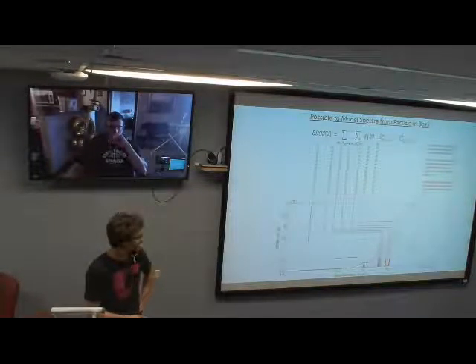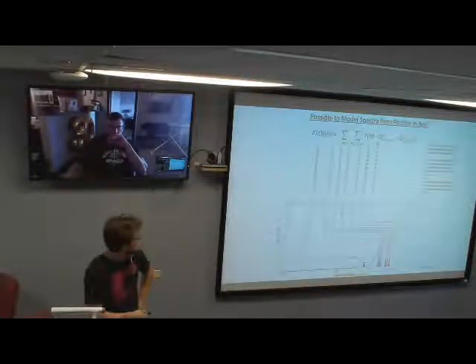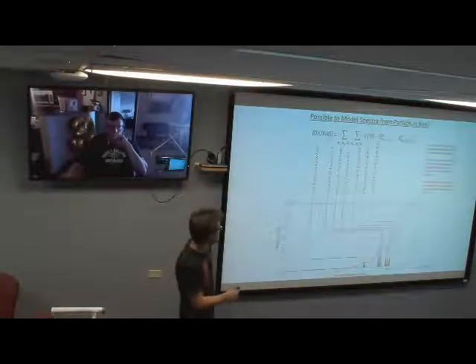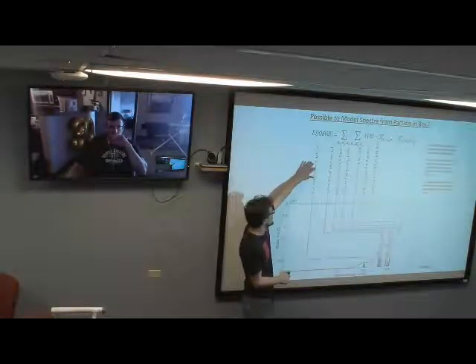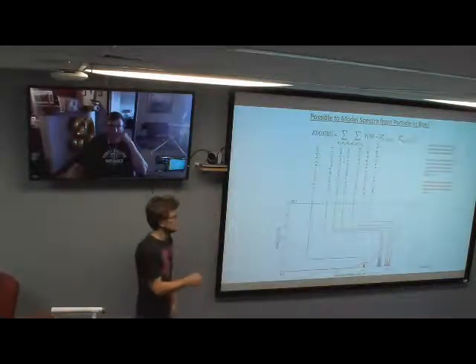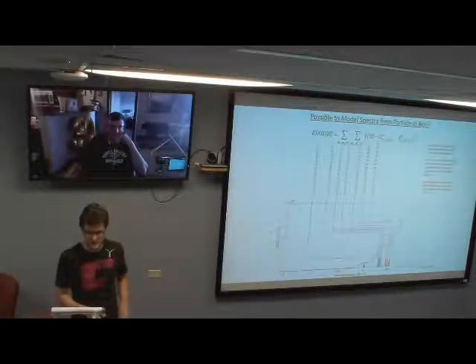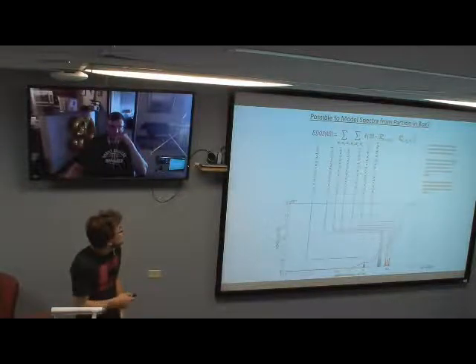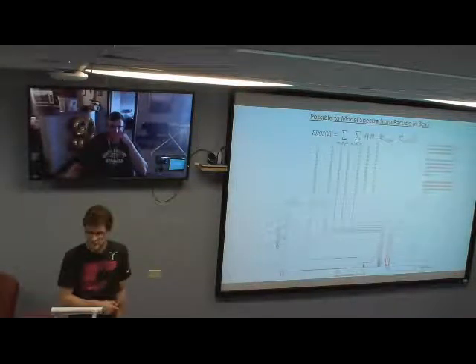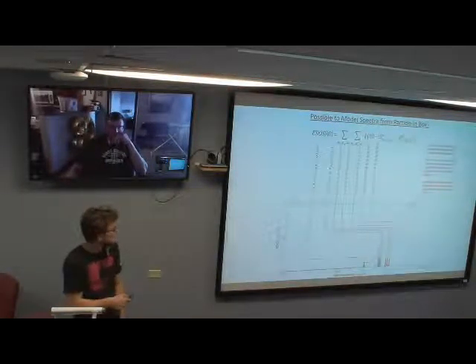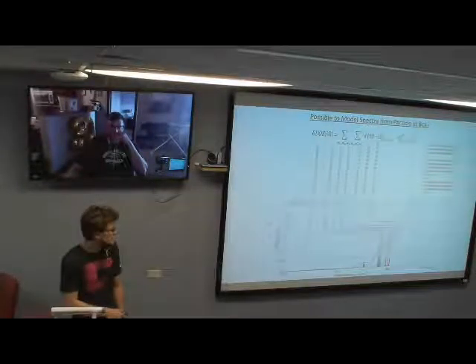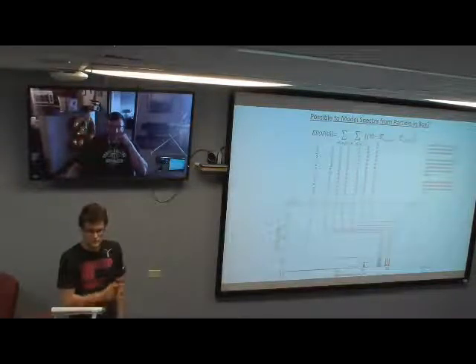Structured, yeah. So the source of these features is quantization between levels. Yeah, so you can see this transition here is basically from the lowest hole and electron state, so your n equals 1 for n_x. How many quantum numbers do you need to identify a single transition? So 6 for each transition for this model. So then the second layer transitions, that would be quantum numbers? So, oh, 3 for electron, 3 for hole?